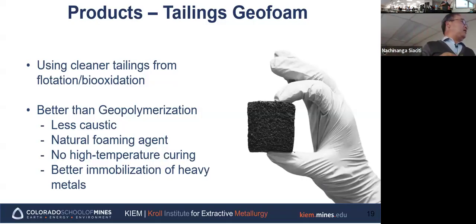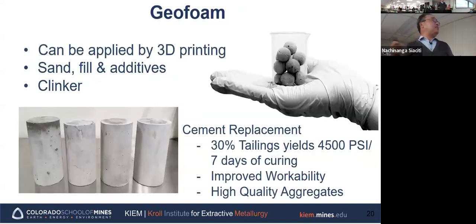But the issue with that procedure is there are still lots of heavy metals, and also a high amount of caustic that eventually works like a leaching agent. So when it is exposed to water, it's going to mobilize the heavy metals. But with a geofoam, you use much less caustic, only enough to activate the materials, and a natural foaming agent, with no high temperature curing, and then better immobilization of heavy metals. So when we go through the different tests, the heavy metals aren't released to the environment.